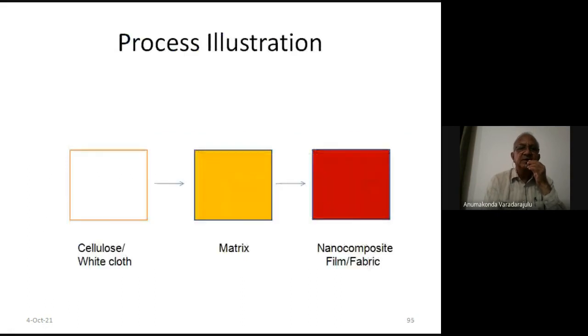Same thing explained here. So the process in a nutshell: cellulose wet film or cloth is white in color or colorless. Matrix is light brown to yellow, and then after dipping it in this, the nanoparticles will be generated because there are leaf extract compounds inside the matrix film, and they react with this metal salt solution which is entering into that particular matrix. So this matrix itself will be acting as a laboratory, and the reaction will be taking place between this leaf extract and the metal salt solution inside the matrix, and then the metal nanoparticles will be generated. As a result, the color of this matrix will change. So the change in color is a preliminary indication of the formation of this metal nanocomposite film.